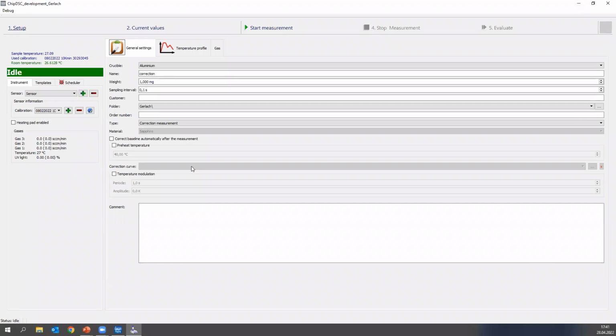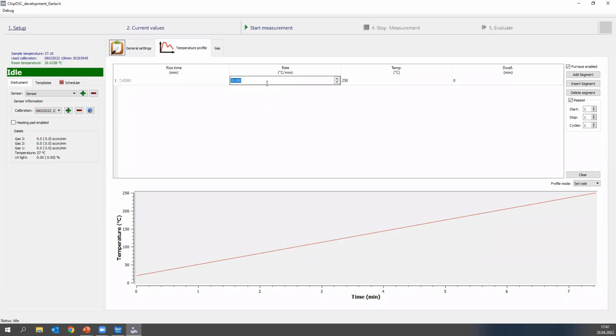If you want to measure with temperature modulation and Chip DSC, don't use any correction curve. This is what the software is doing by itself, so there's no need for any correction curve here. What we have to set up is our temperature modulation. In many cases, I'm using a 60 second period and 1 Kelvin amplitude, and then we can choose our temperature profile. Common practice is something like 10, 5, or 15 Kelvin per minute.